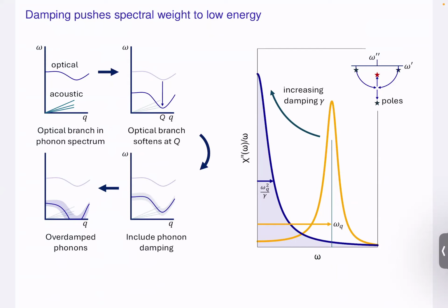Normally, we don't have to consider that. Because if you think of acoustic phonons, for example, there are effectively conservation laws, if you like, or there are good reasons why the phonon scattering rate will become smaller and smaller when the wave vector becomes smaller and smaller. It's a bit like Fermi liquid theory, where the lifetime diverges as the quasi-particle energy approaches the Fermi energy. Likewise, here the phonon lifetime, I think, diverges if the wavelength goes to infinity for acoustic phonons,